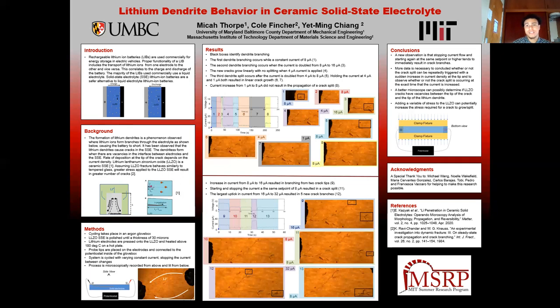In order to visualize this in our entire process, we use a very thin, 30 micron thick, polished LLZO sample of solid electrolyte. We use a thin sample so that the dendrites grow linearly and just across the battery. Lithium electrodes are pressed on and heated up on a hot plate to melt the lithium onto the LLZO. The system is assembled inside of an argon glove box. And then the lithium electrodes are connected to probes and then to the potentiostat, where we can apply constant current to the system, alternating constant current to the system.